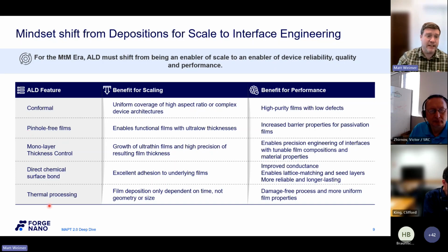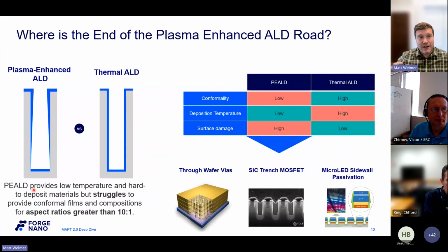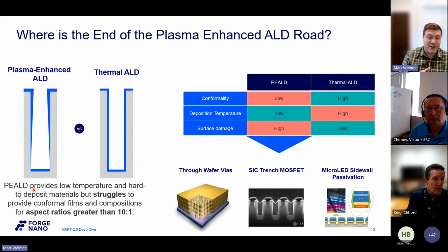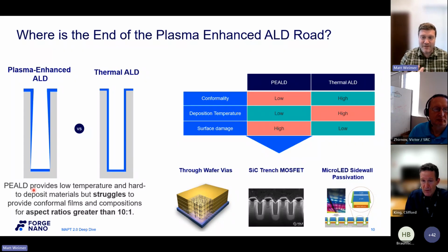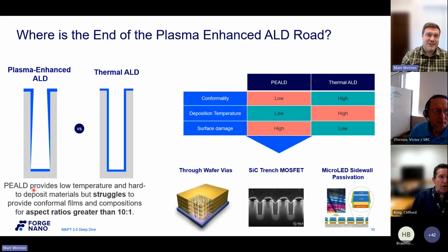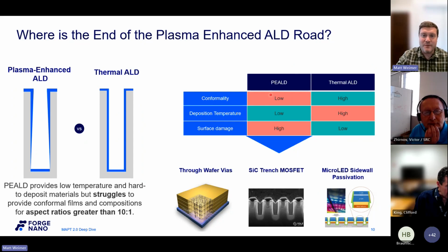Okay, so far I've only talked about thermal ALD and not plasma-enhanced ALD. So again, I'm a chemist, so I don't want to talk out of turn here or denigrate plasma-enhanced ALD. But from a surface chemistry perspective, plasma-enhanced ALD is normally used as a larger hammer. And really, for my money, ALD is a very elegant surface chemistry technique. So let me walk through some of the differences between PE-ALD, plasma-enhanced ALD, and thermal ALD. So if we look at our little table here with the red and green, at some point your conformality will struggle. What that point is will depend on your plasma species. But with thermal ALD, as long as you don't have a high CVD component, you should maintain conformality.